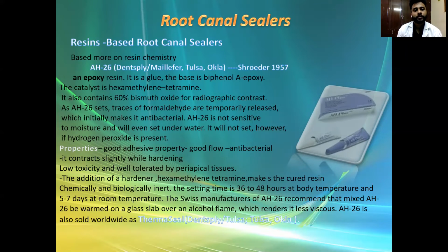AH26 is not sensitive to moisture and will even set underwater. It will not set, however, if hydrogen peroxide is present. It has a very good adhesive property, good flow, a good antibacterial action, and low toxicity, and is well tolerated by periapical tissues. The addition of a hardener, hexamethylene tetramine, makes the cured resin chemically and biologically inert. The set time is 36 to 48 hours at body temperature and 5 to 7 days at room temperature.